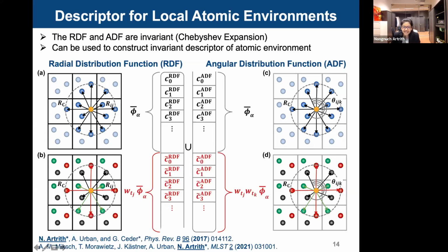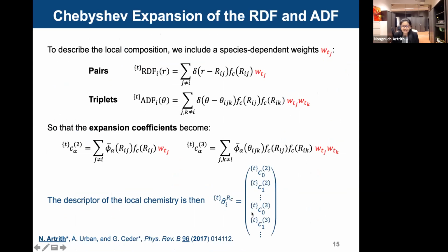And so describing it as a cartoon is not that easy to understand. Sometimes it's easier to look at equations than just the cartoon that I showed before. Here are the equations of the Chebyshev descriptors for the local chemical species or atom type T that I just discussed before. The descriptor components are the expansion coefficients of the RDF and ADF, and the weights, W_TJ, like you can see here, are specific for the atomic species. So the descriptor for the local structures, if it's equivalent, so all other weights are equal to 1, for example, like you can see here.